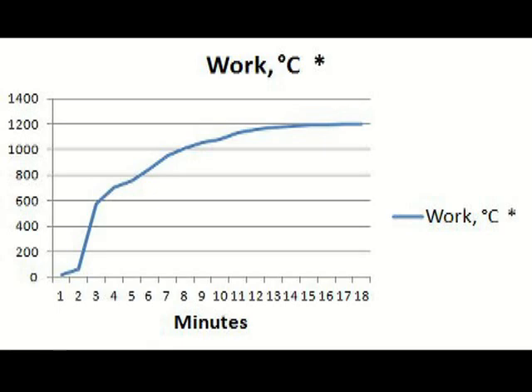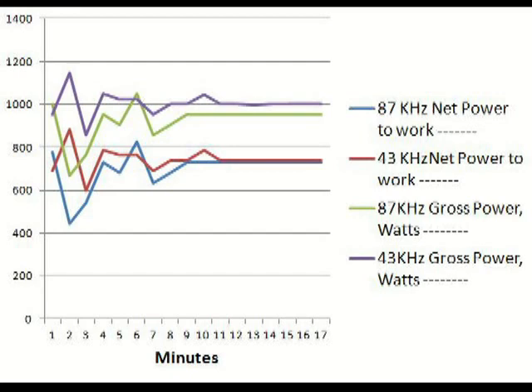So this heating profile is for reference only since I only have the one test. Power in watts. We certainly do get 1000 watts out of the system at either frequency, don't we? You see somewhat different initial currents due to my work loading process. The slightly lower steady-state current later in the 87 kilohertz test is not related to the difference in frequency in my opinion. The idle current at 87 kilohertz is slightly less than it is at 43 kilohertz, 4.7 amps versus 5.5. This makes the net current delivered to the load, which is the work, almost identical for both frequencies.